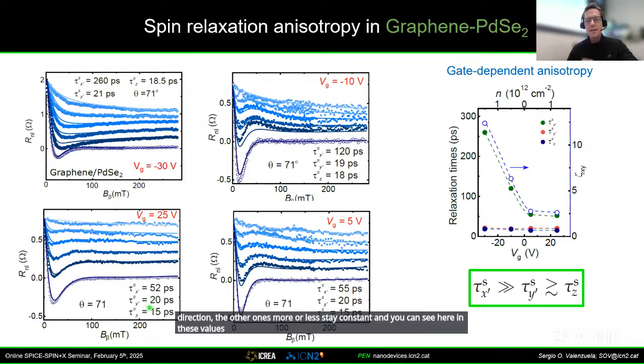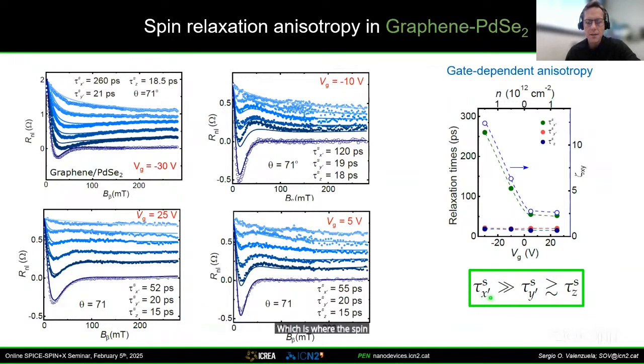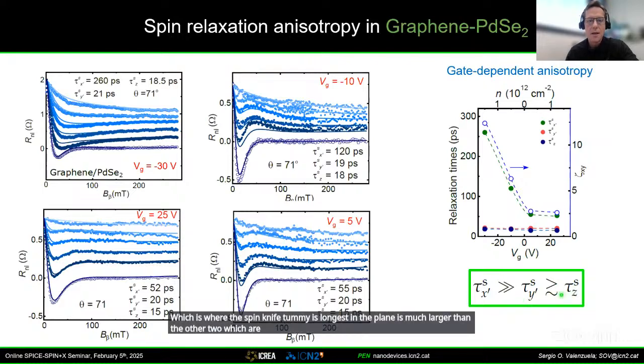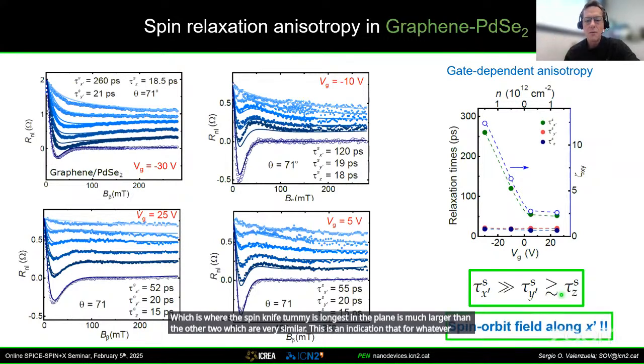So this indicates in all situations that the spin lifetime in this direction, which is where the spin lifetime is longest in the plane, is much larger than the other two, which are very similar. This is an indication that for whatever reason, the spin orbit field is along X prime in this device.